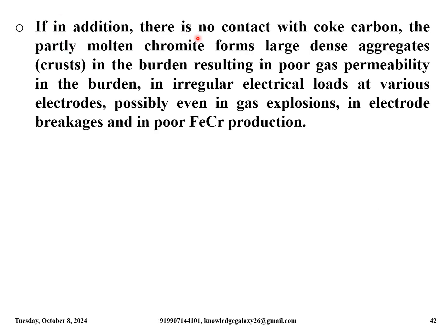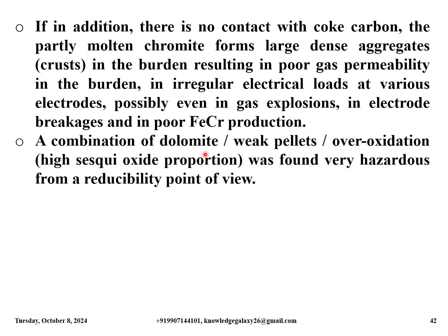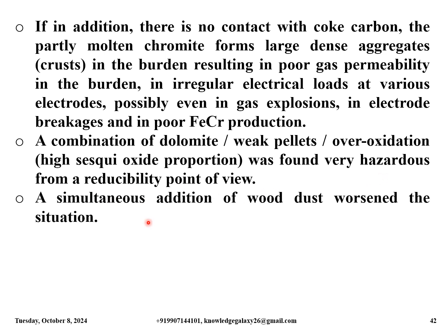If, in addition, there is no contact with coke carbon, the partly molten chromite forms large dense aggregates, that is, crust, in the burden, resulting in poor gas permeability in the burden, in irregular electrical loads at various electrodes, and possibly even in gas explosions, in electrode breakages, and in poor ferrochrome production. A combination of dolomite and weak pellets and over oxidation, that is high ferric oxide proportion, was found very hazardous from a reducibility point of view. A simultaneous addition of wood dust worsened the situation.